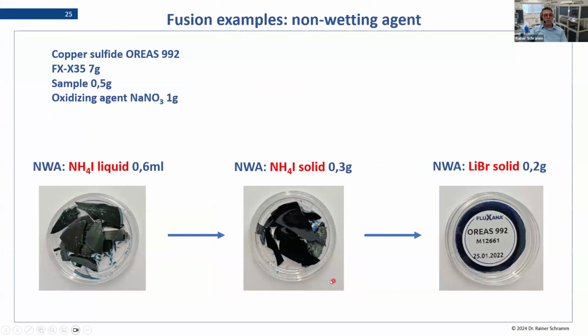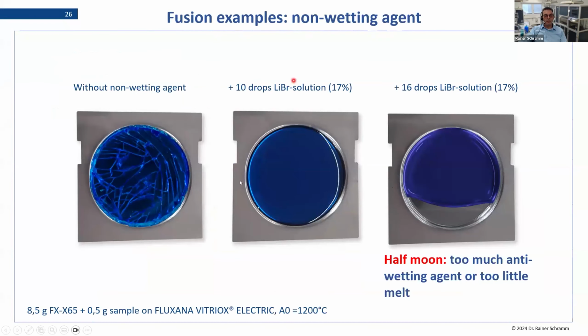Here I have an example where I use a copper sulfide, so copper as an element which sticks a lot to the mold. So we get here a lot of tension, it will crack, and we add then some iodide to compensate this. And you see, the more you add, then suddenly you get a glass. And this is for iodide. And here I have another example with bromide, same story. This copper-based bead is sticking to the mold, and while this is shrinking in the cooling process, it just cracks.